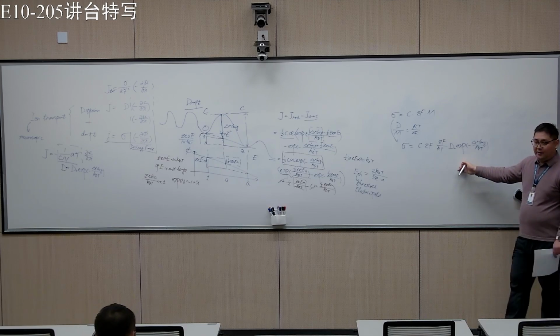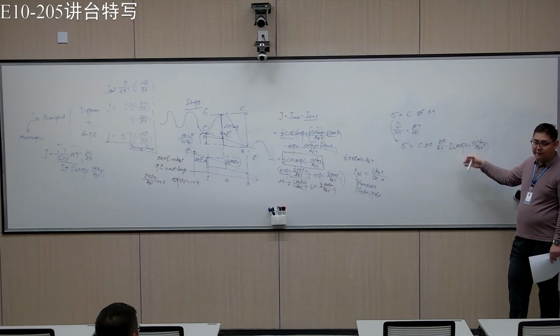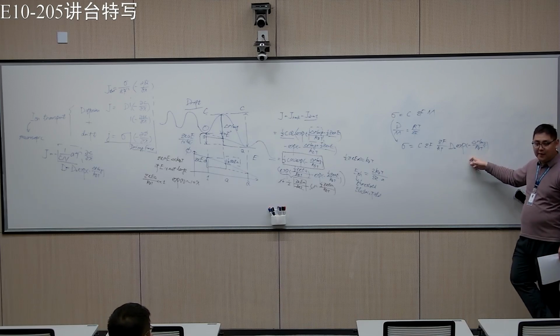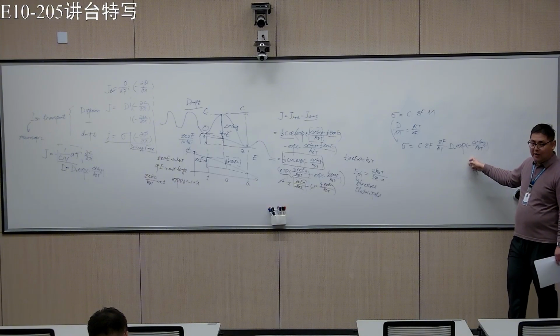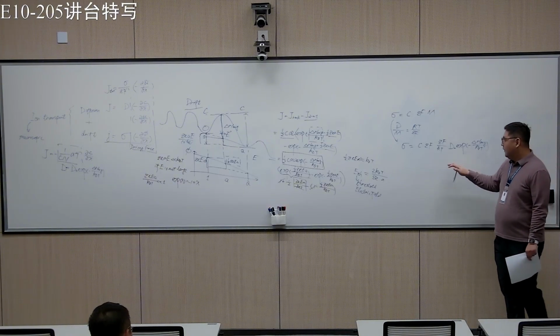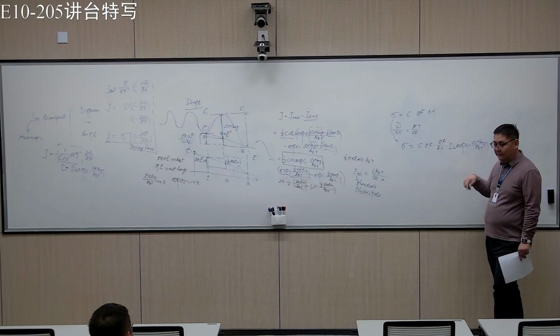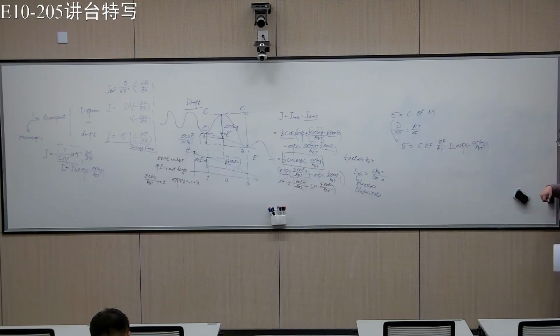So for the ionic picture, we have something like this. For the electronic picture, only when we have so-called polarons, where the electrons are bound to ions, do we have something like this. So this is not usually true for electrons in the valence band or conduction band.